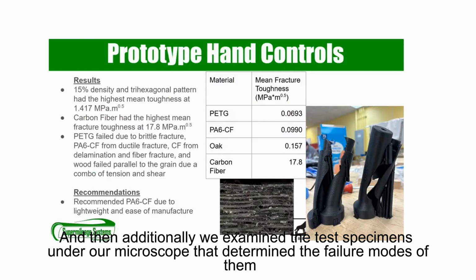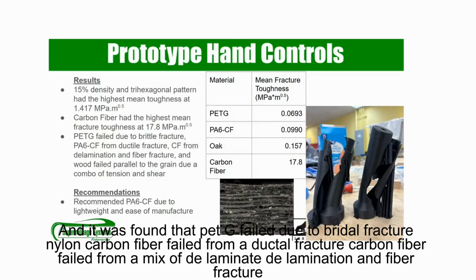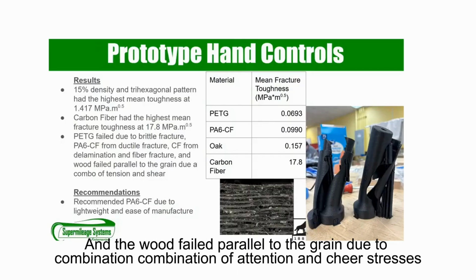And then additionally, we examined the test specimens under a microscope to determine their failure modes. It was found that PET-G failed due to brittle fracture, nylon carbon fiber failed from a ductile fracture, carbon fiber failed from a mix of delamination and fiber fracture, and the wood failed parallel to the grain due to a combination of tension and shear stresses.